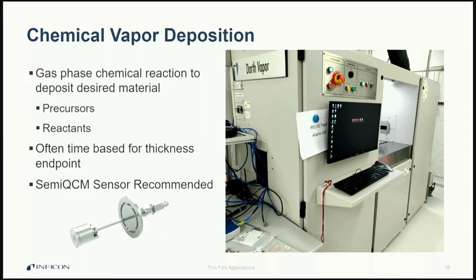Because of this, QCMs are not always considered for monitoring the deposition rate and thickness of CVD applications. However, QCMs are proving to be more valuable in these applications to monitor other things, such as verifying precursors passed through the chamber, verifying that chamber clean endpoints have been reached, and also for providing other data points to ensure chamber stability. In these situations, a type of semi-QCM sensor is recommended to be used together with FabGuard.